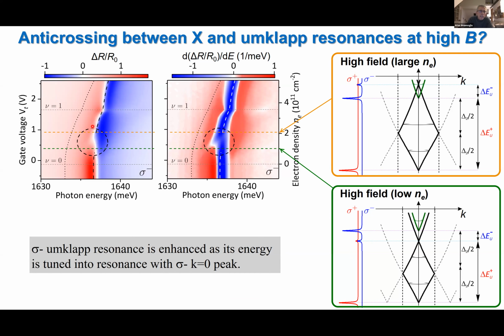So you can see here that even without differentiation, we now see the signature of the Umklapp resonance crossing into the main exciton peak, the sigma minus polarized peak. And if you differentiate it, then you can discern the Umklapp peak much better.